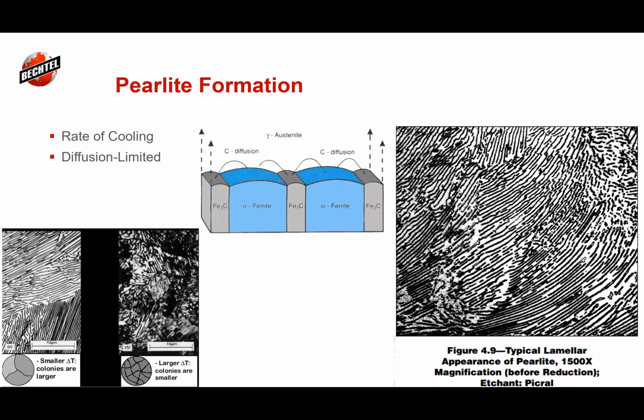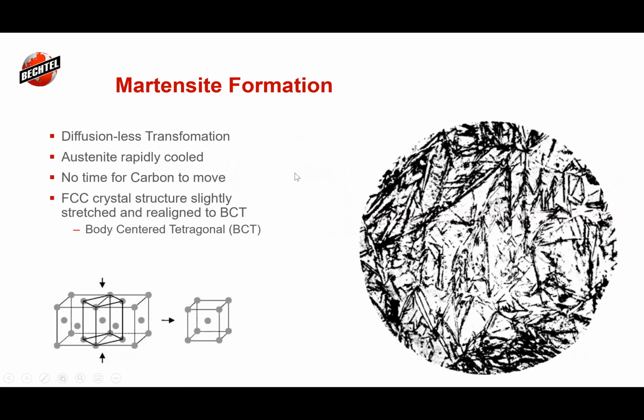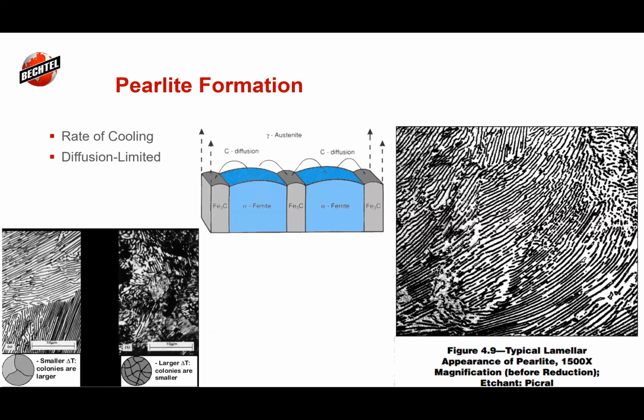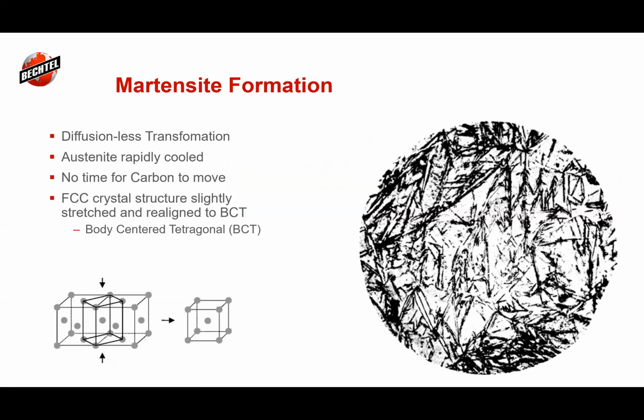If we're able to slowly transform from austenite to ferrite, and our heat affected zone has time to cool down nice and slowly, then we form this perlite, and it's a nice distribution of ferrite with laths of iron carbide or cementite that form in the middle. And so this is diffusion limited. It's based on the carbon atoms moving through the matrix. If we don't give the perlite enough time to form, this is the martensite.